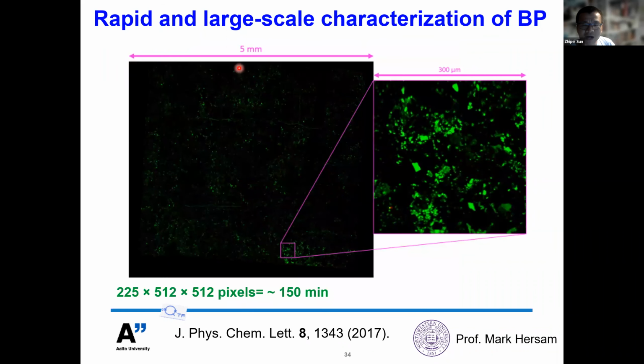Again, here I would like to highlight the fast and large-scale characterization advantages of third harmonic generation. For example, we are able to measure samples of around 5 by 5 millimeter square in only around 2 hours. We are able to fully characterize the thickness and also the crystal orientations of the flakes during the experimental measurements. So this is really quick for our research.